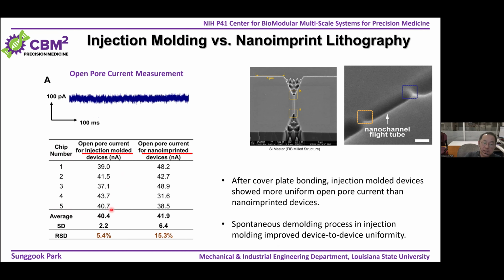What surprised us is that the variation of this open pore current is way lower for the samples produced by injection molding compared to those produced by nanoimprint lithography. So even though the throughput of injection molding is way higher than nanoimprint lithography, the sample uniformity is also higher. And we thought about why it happens.